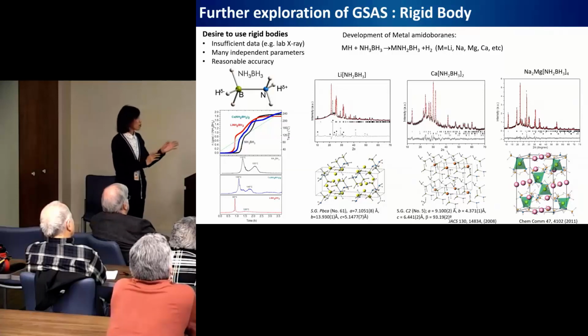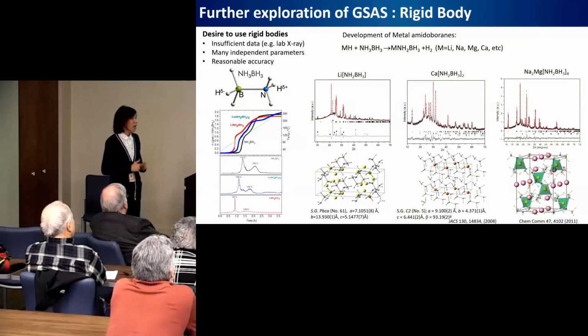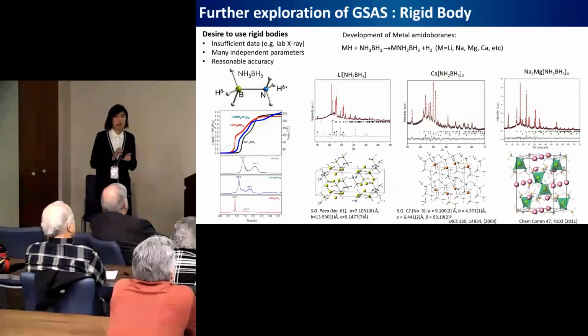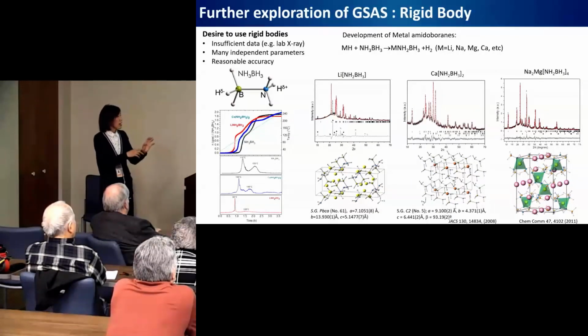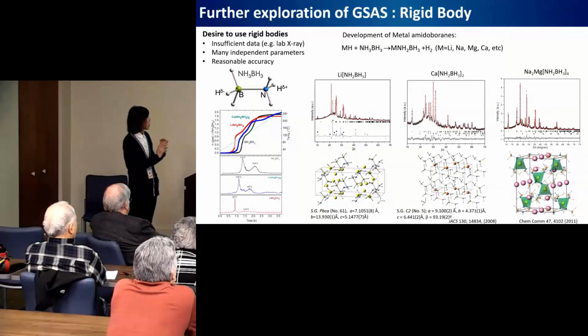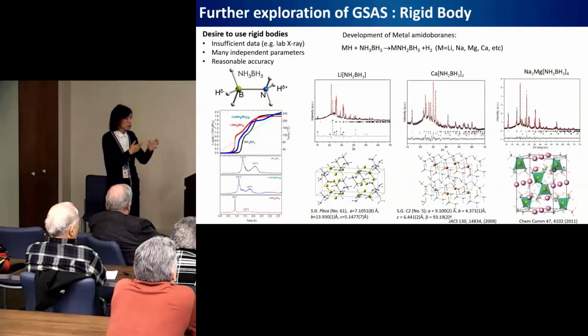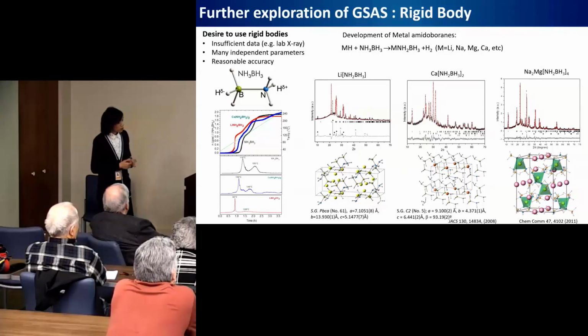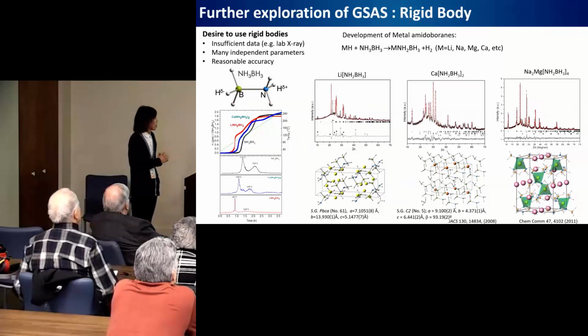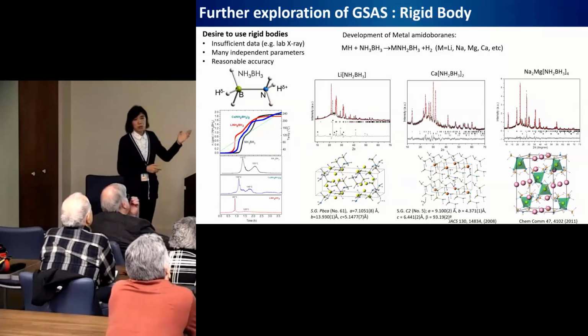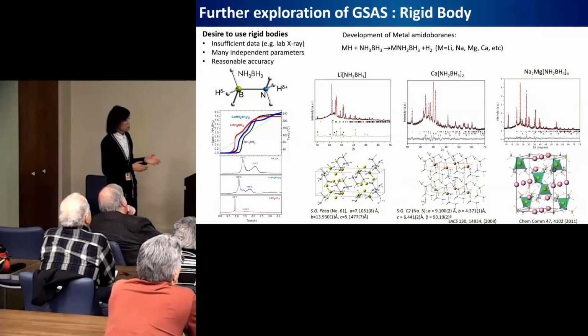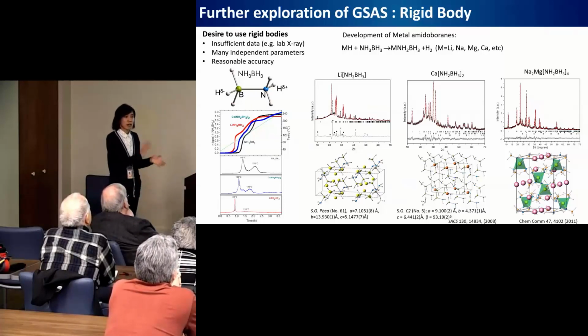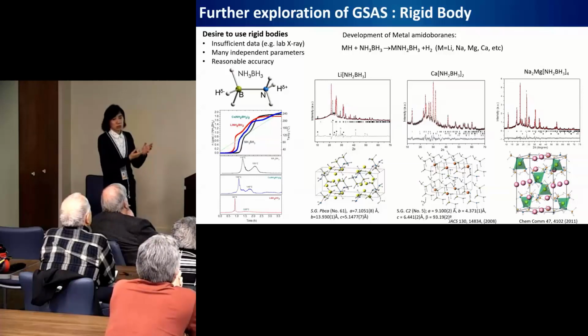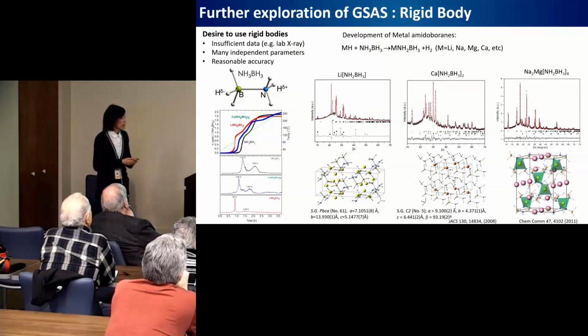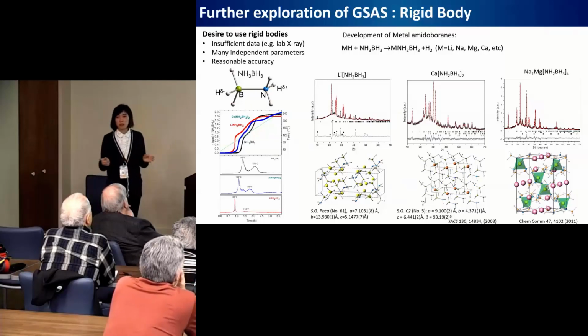And of course, because these are lightweight hydride materials, we also did DFT calculations to relax the structure and get an optimized orientation of those amidoborane ions with the lowest energy. And then once we have a proper structure model, we want to refine the structure. Ideally, we should do neutron diffraction. But as you can see, those compounds contain boron and hydrogen, so we have to do isotope labeling. And also, we need a large quantity of sample for neutron diffraction, which is very time-consuming and costly.